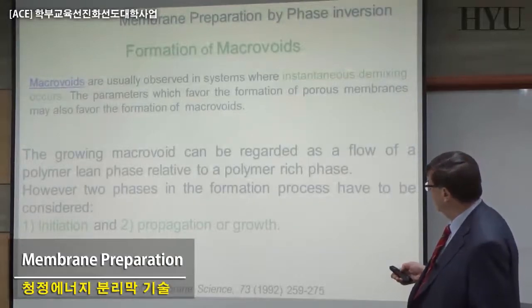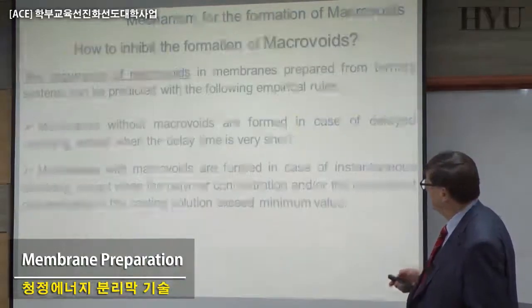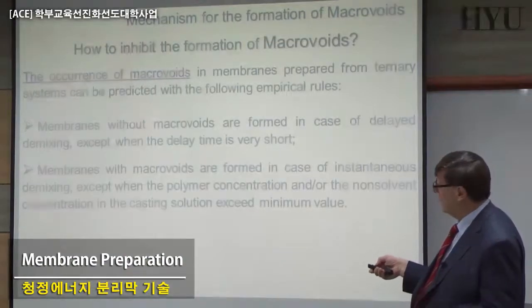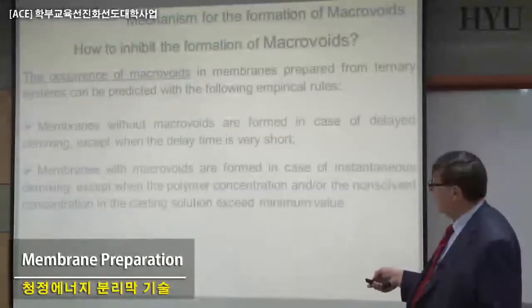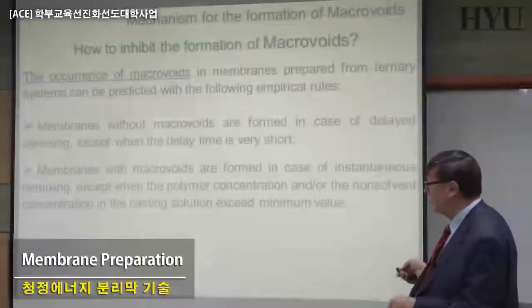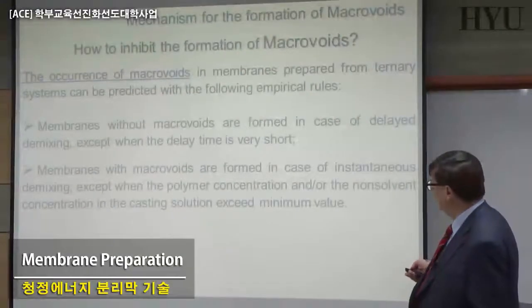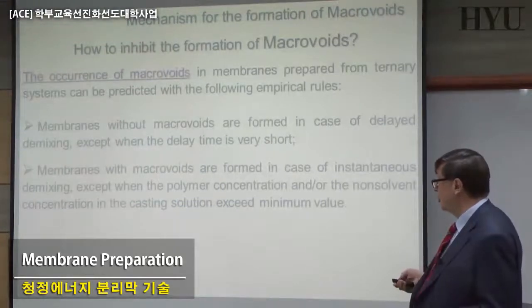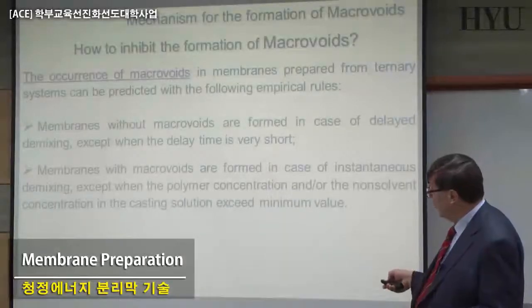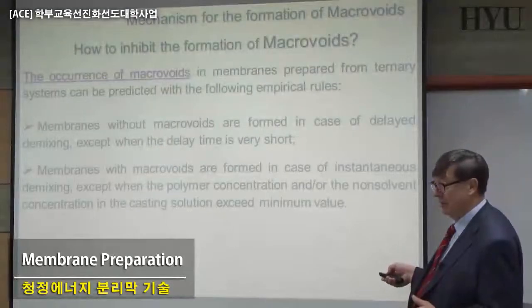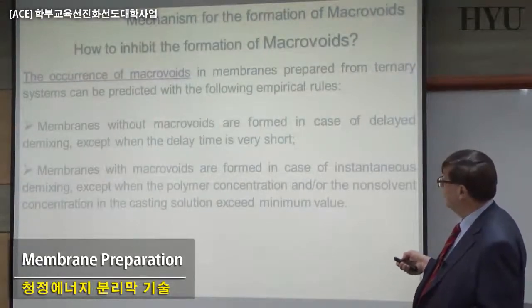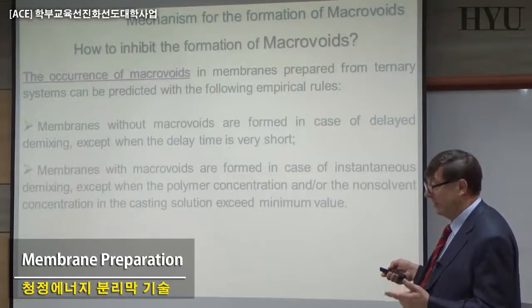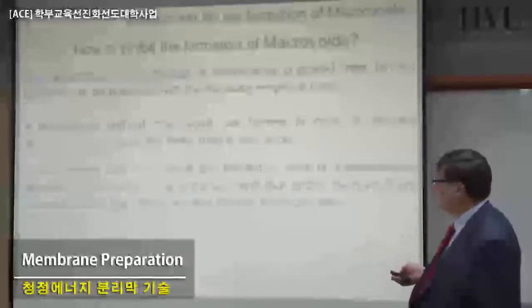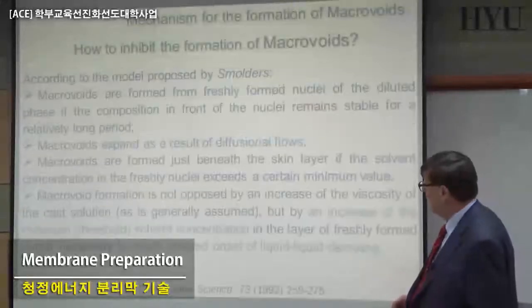Basically, to reduce macrovoids, normally you have membranes without macrovoids in case of delayed demixing, and the membranes with macrovoids are formed in case of instantaneous demixing, as we saw already before, except when the polymer concentration and the non-solvent concentration exceed a very low value. So also these rules are not 100% valid. The system is complicated because the possibility that you're trying to avoid the macrovoids by inducing instantaneous demixing can be related also to the amount of the non-solvent concentration in the system.